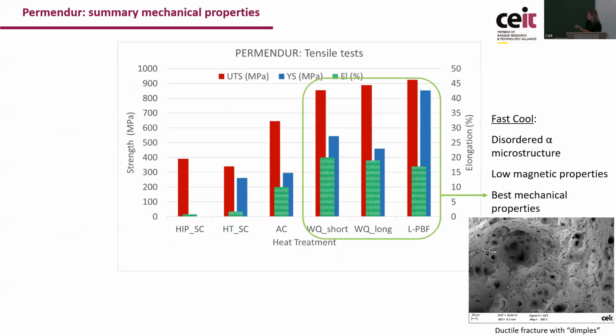So, conclusion: if we have a material that has been fast cooled from AM or after heat treatment, we are going to obtain a material that has a disordered alpha microstructure, which has very good mechanical properties, both in strength and in elongation. And as a sample, you can see here a fracture surface of a very ductile material, but that has very poor soft magnetic properties.